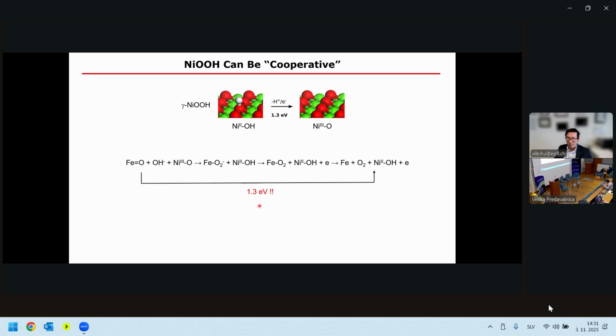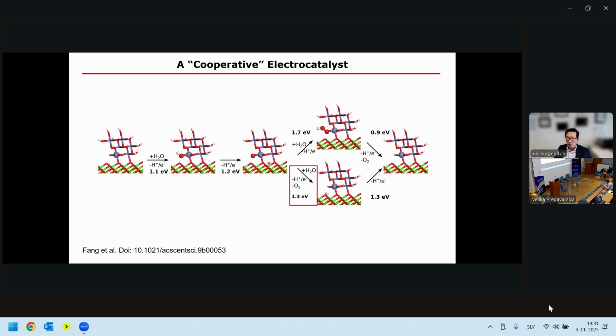So by having this cooperation, we go through this pathway, where the nickel OOH acts as a redox equivalent to take a hydrogen atom from the hydroxyl species, really promoting this catalysis, and we have a really active catalyst. So that's for the anode catalyst.